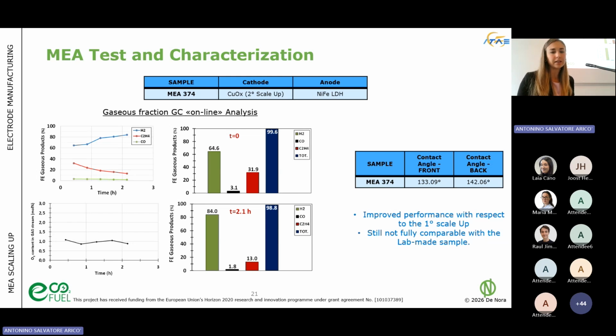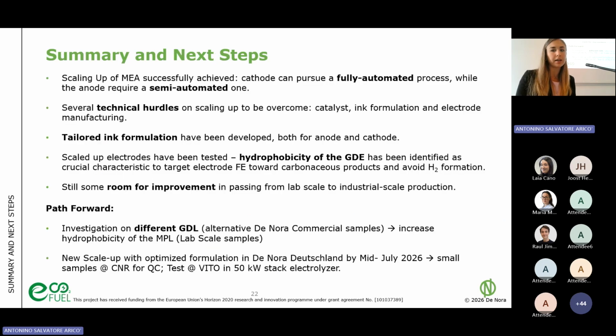So we were able to increase the performances. The hydrophobicity is reached, but again, we are not reaching the same results as the lab scale. I mean, it's still good because we do have nice production of ethylene and carbon monoxide, but it's still lower than the one obtained at the lab. So that's a starting point on which we want to work. Regarding the sintering, we worked on the sintering, but we are also planning to work on a different GDL structure in order to increase again the hydrophobicity of the GDL.